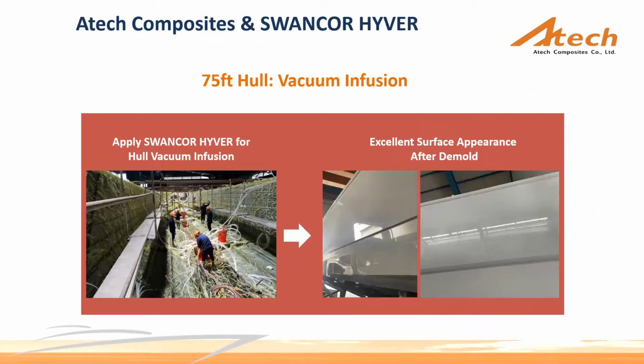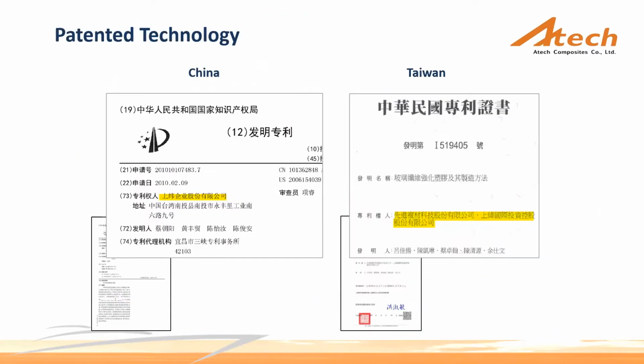Then this is the biggest trial production part of HYVER application in our factory. It was a 75 feet yacht hull. We infused the whole shell, girders, and stringers in one shot. Basically, the surface above the chine line is a high visibility area when it sits on the cradle. So you can see the reflection was straight. You can even see a deck house reflection on the top side. The surface was really, really great.